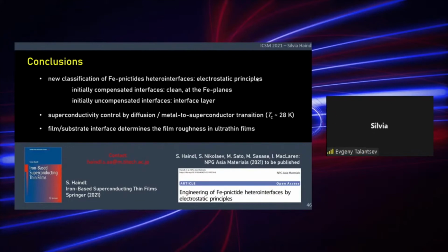Yes. So in the case of the iron pnictide thin films, we use quite high deposition temperatures, and these deposition temperatures are in the range of 850 degrees C. So if I grow these bilayers, for example, the iron oxypnictide on the barium 122, the substrate was MgO, and the temperature was constant at 850 degrees C during the deposition. When you grow the barium 122 on MgO alone, you can decrease this substrate temperature a little bit. However, it was maybe similar, 800 to 850.